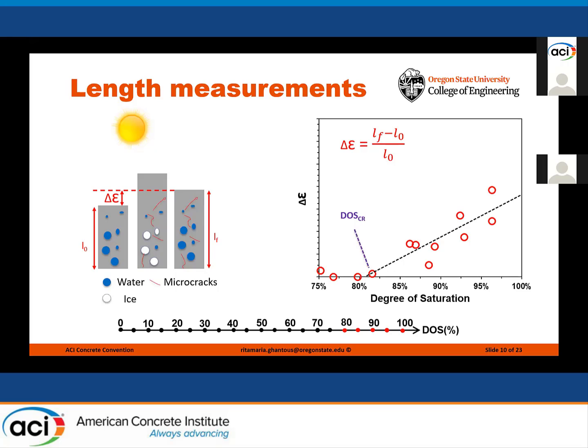As you can see in this graph, the samples with high DOS on the x-axis develop residual strain with positive values above 0, while for samples with a DOS below a critical value, the residual strain will be equal to 0, which indicates the absence of freezing and thawing damage.